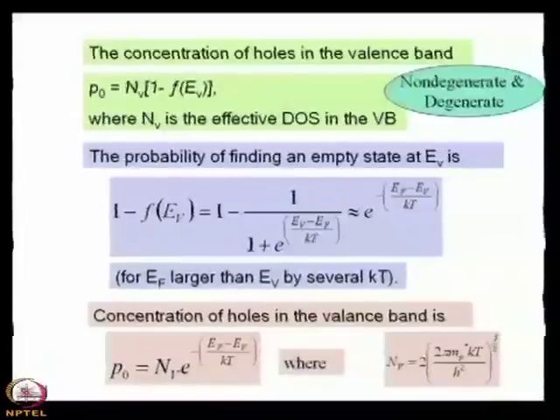Remember: all such statistics are related to non-degenerate semiconductors, where the number of electrons in the conduction band or the number of holes in the valence band is less than the density of states of the corresponding bands. So it is applicable up to carrier concentrations of 10¹⁷–10¹⁸. If it exceeds 10¹⁹ or 10²⁰, you cannot use these expressions.